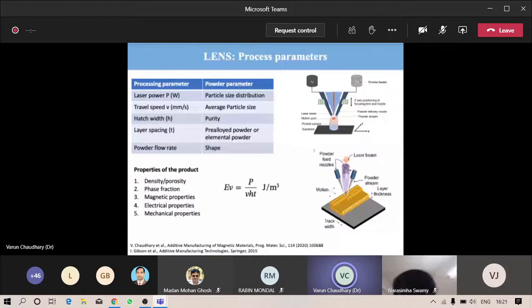This LENS technique has several process parameters, and by tuning these process parameters, we can tune the final product property. For example, laser power, travel speed, hatch width, and lane spacing. And these all affect the final product properties. Powder parameters also affect the final product properties. So for some powders, a particular powder size distribution is required. If you want to switch to other materials, it may be a different size distribution requirement.